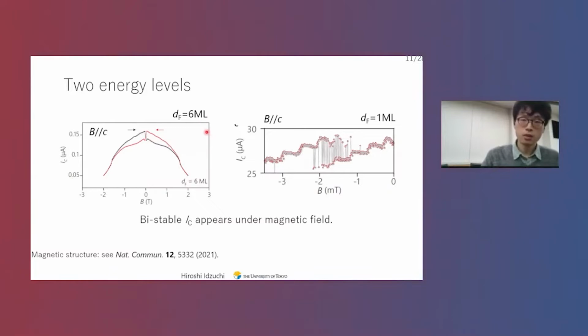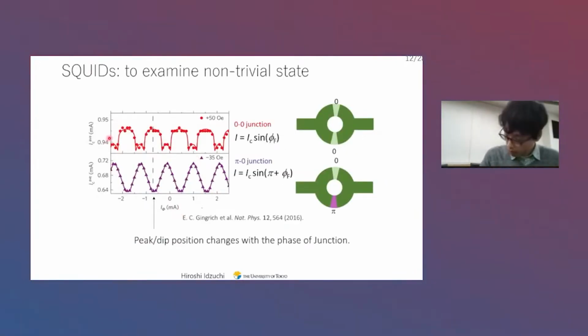That kind of hysteretic behavior implies two energy levels, and it is seen in both the six-monolayer case and the monolayer case. And we wondered what it is, and then we constructed SQUIDs with this CGT tunneling junction. This is to explain the basic principle of SQUIDs with Josephson junctions with zero phase and pi phase. If your SQUID has two zero-phase Josephson junctions, you have a maximum current at zero field, while if you have a zero-pi junction, your critical current is minimum at zero field.